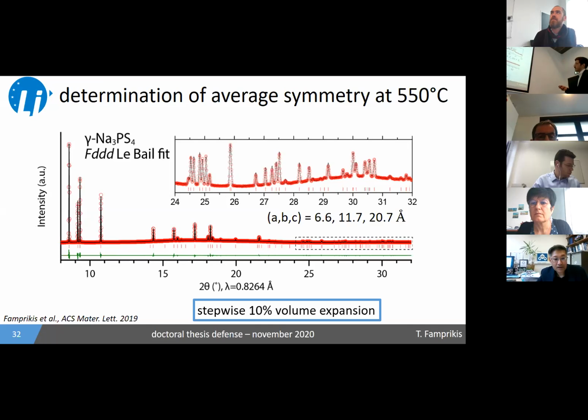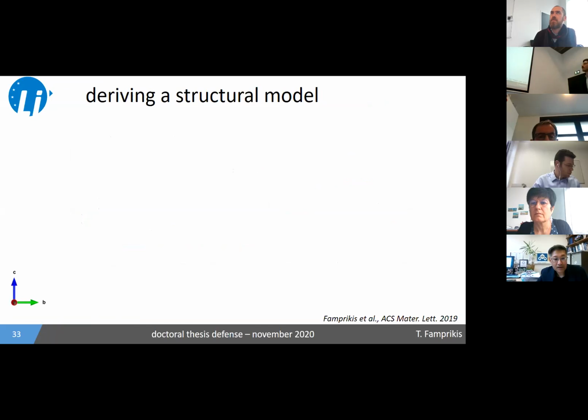And according to these lattice parameters, this also represents a stepwise about 10% volume expansion upon transition from the beta to the gamma phase. So from having the average symmetry and the size of the cell, we would like to now have a more structural model of how the thing looks on the atomic scale.